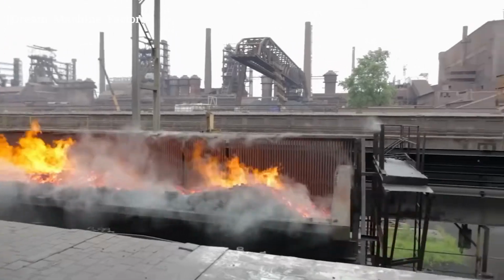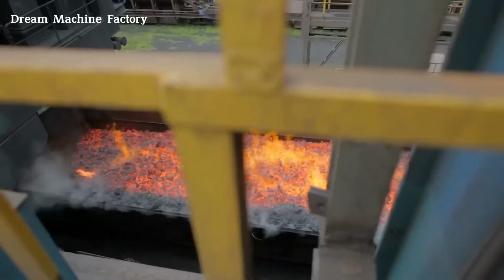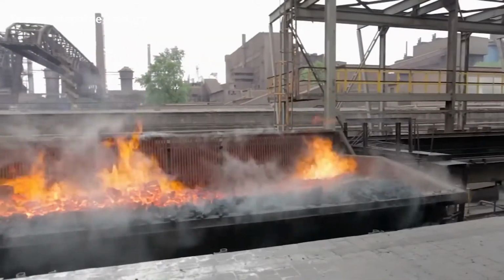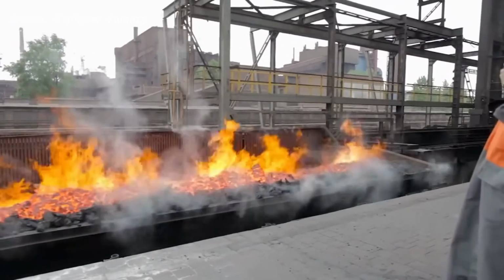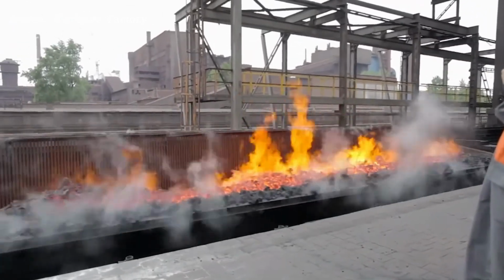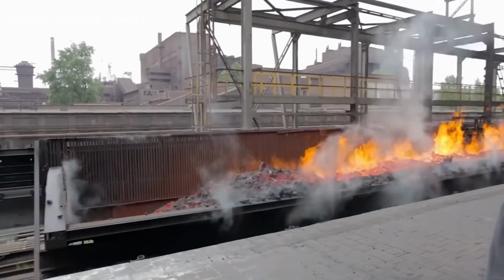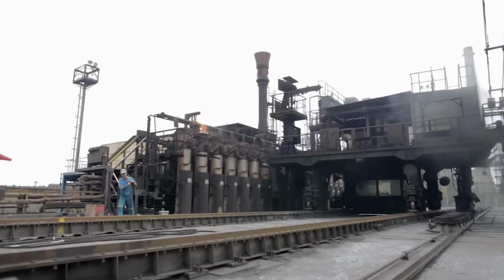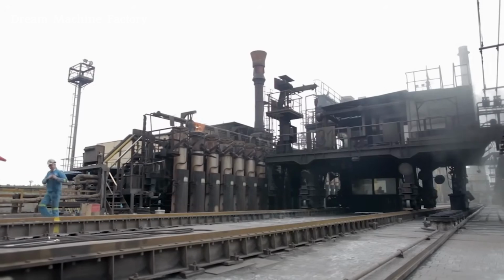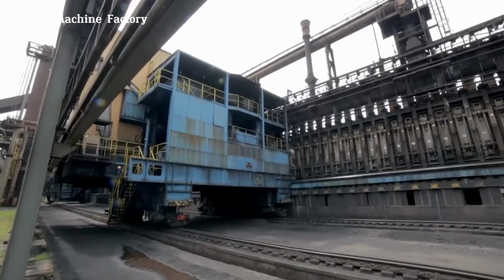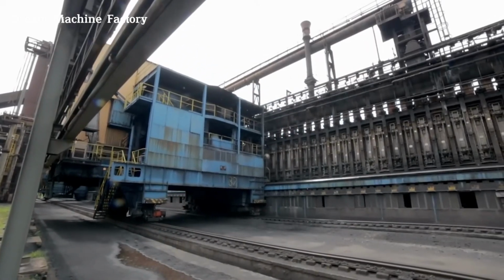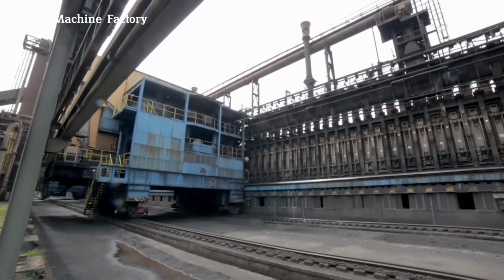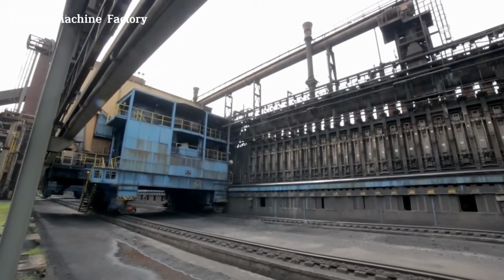into its final form. The steel-making process begins with the production of coke, a carbon-rich material derived from black coal. In a facility called a coke oven battery, pulverized coal is heated to around 1,100 degrees Celsius in the absence of oxygen for about 24 hours. This heating drives off volatile components, leaving behind a gray-silver, porous, and highly combustible solid: coke.